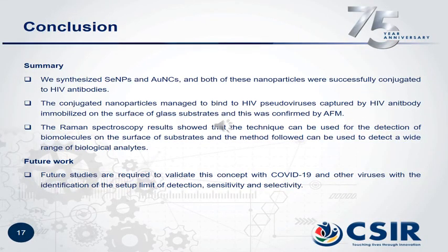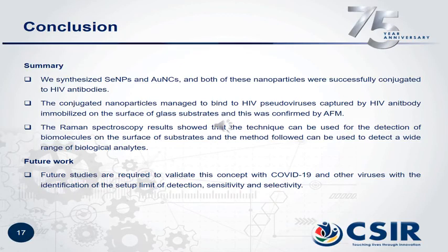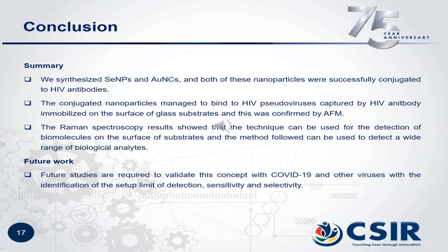In conclusion, we synthesized selenium nanoparticles and gold nanoclusters, and both were successfully conjugated to HIV antibodies. The conjugated nanoparticles managed to bind to HIV pseudoviruses captured by HIV antibodies immobilized on the surface of glass substrates, as confirmed by atomic force microscopy. The Raman spectroscopy results show that the technique can be used for the detection of biomolecules on the surface of substrates and the method can be used to detect a wide range of biological analytes. Future studies are required to validate this concept with COVID-19 and other viruses, with identification of the setup limit of detection, sensitivity, and selectivity.